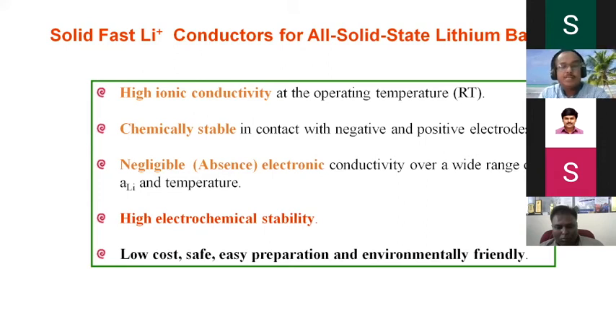It should be chemically stable in contact with the negative and positive electrodes. There should be no decomposition when it starts to react with metallic lithium or when the positive electrode is considered. And above all, your electrolyte should have negligible electronic conductivity, something around 0.99 transference number.